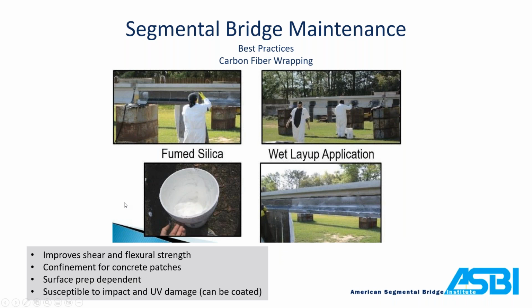Carbon fiber wrapping improves shear and flexural strength if you need it to. It's also for confinement for concrete patching. I know sometimes it's difficult to do an overhead patch and have it stay in place. So covering that with some carbon fiber can help hold that concrete in place. It is surface prep dependent. You've got to have a clean surface like a lot of other things. And carbon fiber is susceptible to impact and UV damage. Hit it with a hammer, it's going to break. And it doesn't like the sunlight, so you want to have a polyurethane surface sealer over top of it to protect it against UV once it's complete.